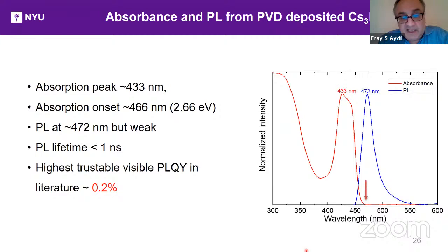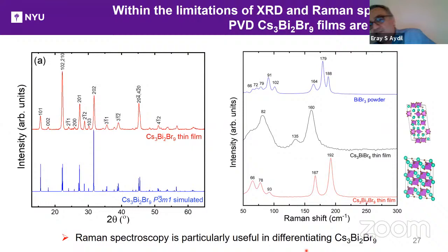And if you throw away all the data that is suspect, the highest trustable photoluminescence quantum yield in the literature is actually 0.2%. So whether this material emits very efficiently is certainly in doubt, at least in the visible. I should also say that we made a lot of oleic acid solutions with very high photoluminescence quantum yield, with the quantum yield depending on who you get the oleic acid from and what the impurities are. So the message here is that one has to be very, very careful in doing optical measurements here. So I want to get back to my story. I told you a lot about this optical absorption, but the fact that this material has low photoluminescence quantum yield in the visible is important, okay?